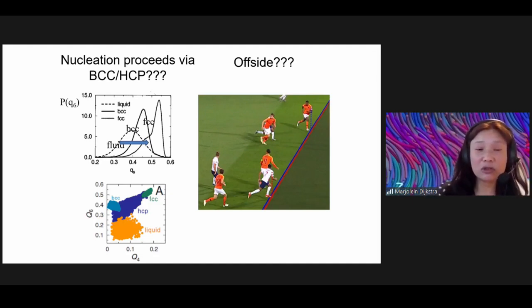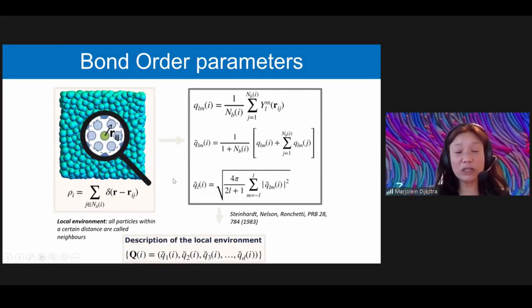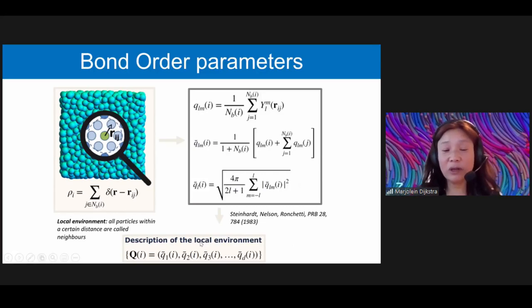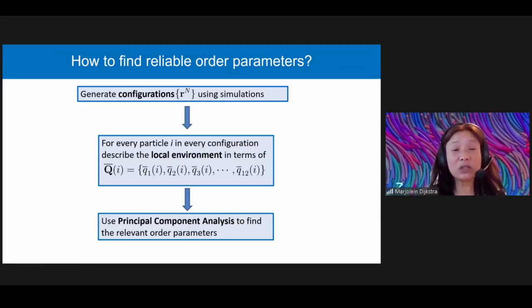So what we decided to do is not only take Q4 and Q6, but use the full expansion of the spherical harmonics. We use Q1 all the way up to Q12 or Q24, and we make a very big vector of this for every particle. So we do simulations, we generate configurations, and for every particle i in every configuration, we calculate this vector.